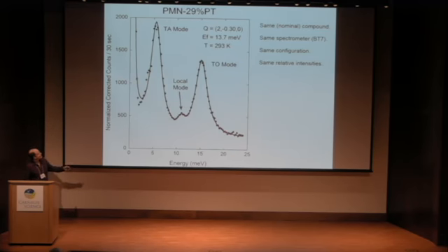And this is at a wave vector of 0.3 reciprocal lattice units measured from the 200 Bragg peak. All my data are at room temperature. Okay? And this is for a fixed final energy of 13.7. You'll see these numbers change a little bit during my talk, but these actually represent an important parameter that we can tune to try to test our results.